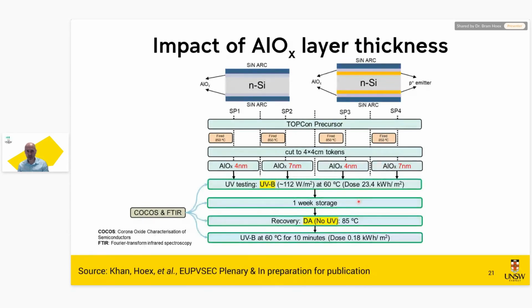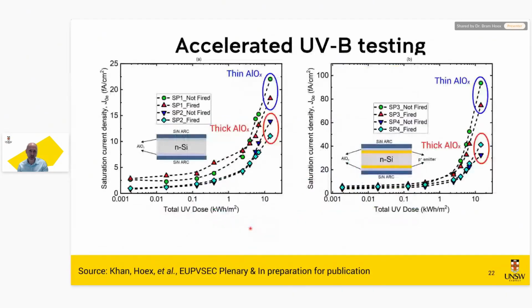We look at the effect of dark storage. We look at dark annealing that has been shown to recover it. I will show you some concrete evidence of that later. And then we also look at what would happen if you would measure the sample a few times. We'll show that that's actually equivalent to exposing it to UV.